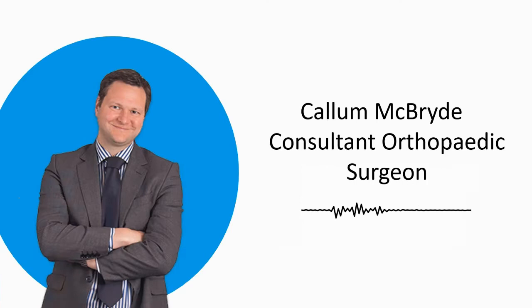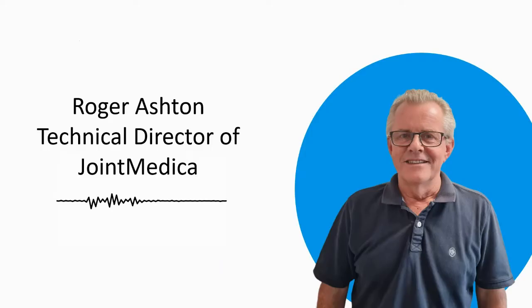Roger, you're an engineer who's been involved a long time with the Birmingham hip and now with Polymotion, and you've been very much involved in retrieval work. Tell me about retrievals you've seen. It's been quite a privileged position. There is a resounding message from retrievals: wear is a function of where the bearing contact position is in the device — where the head operates within the cup. That's a function in broadest terms of how the cup is placed, in anteversion and inclination, but also a function of impingement effects. It has been possible to see a low-level message associated with impingement of the device and its effect on wear. When the contact position starts to stray towards the edge of the device, you start to see elevated wear, and as it strays further, more pronounced edge wear where lubrication breaks down.